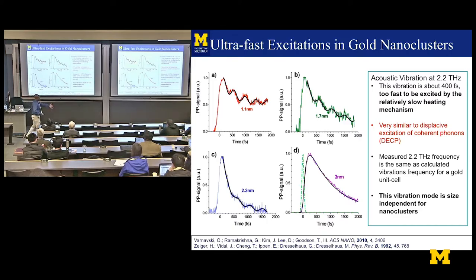Again, this is basically looking at that chain link fence, right? You kick it down one end, and it's doing this vibration as it goes down the energy level. Well, you can measure this acoustic vibration at 2.2 terahertz. So this vibration, this is the period of that. This vibration is about 400 femtoseconds. And that's too fast to be excited by the relatively slow heating mechanism. So if it was just heating, like in the big particle, it could never relax in this kind of time scale. But instead it was very similar to the so-called displacive excitation of coherent phonons, okay?